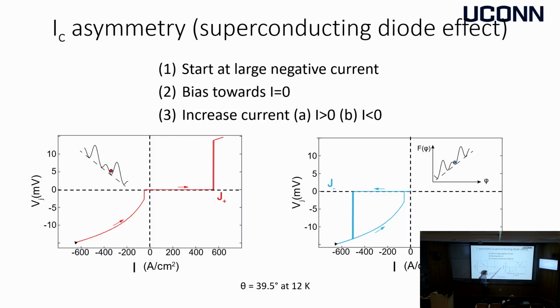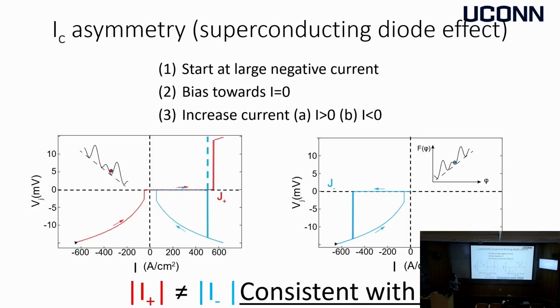You again get voltage. You do the same experiment, but after going into the superconducting state, you actually increase the current in the opposite direction. And then what you need to do is compare the values of those critical currents in the two directions. You can see that they are different. And in principle, it is consistent with a broken time reversal state.